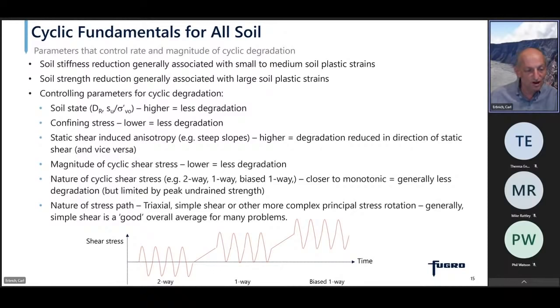With confining stress, lower values lead to less degradation, which actually is linked very much to soil state. So those two are intrinsically linked anyway. Static shear-induced anisotropy, for example, on very steep slopes or under heavily loaded foundations. The higher this is, the degradation is reduced in the direction of the static shear, but actually vice versa. In the other direction, we get more degradation. But fortunately, in these sorts of problems where we do have high static anisotropy, it's usually the improvement in the downslope direction for a slope that matters. And it's important to consider that, because otherwise you will predict slopes that will fail that actually will not fail.